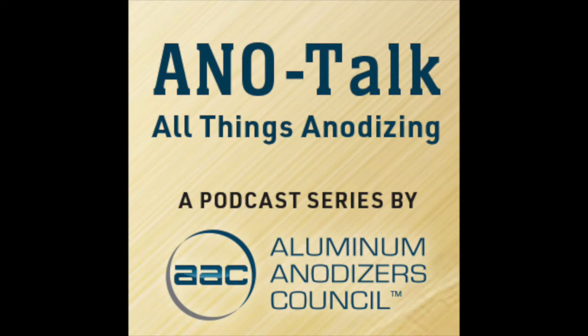So, okay. Jack, how familiar are you with the difference between caustic and acid etch? Well, listen, they both have their own benefits. I think acid etch was a great invention, especially for when you want to get these matte looks, I'll call them dull, if you will, but I don't know if dull's the right word, but certainly a matte finish without losing a lot of material. The sodium hydroxide from the etch tanks tends to chew up the aluminum at a controlled rate. But as George will tell you, the metal removal is much greater in a caustic etch than in an acid etch. Oh yeah, for sure. So if you're dealing with tight tolerance extrusions, you might want to consider an acid etch over a caustic etch.